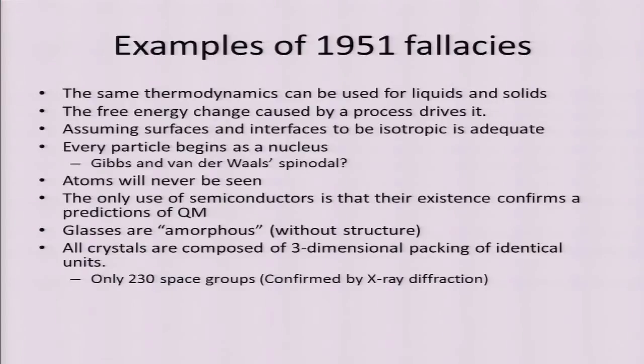Okay, fallacies in my time. The same thermodynamics can be used for liquids and solids. I did a lot of work with Larché to show that the elastic effects of compositional inhomogeneities and so on can't be ignored, and certainly the elastic effect in spinodal decomposition can't be ignored. The free energy changes caused by a process drives it. Assuming surfaces and interfaces to be isotropic: until recently, practically nobody allowed a surface to be anything but isotropic, even though every microstructure that you saw had corners and facets and so on.